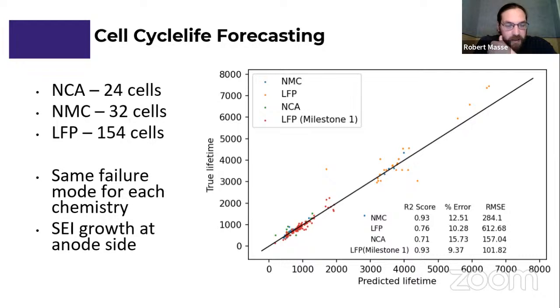chemistries. NCA, that's nickel, cobalt, aluminum. NMC, nickel, manganese, cobalt. LFP is lithium iron phosphate. These are 3 of the most common cathodes for batteries today. What we were able to find is that since the anode side is where the main failure mode is, that being SEI growth on the anode side, on the graphite anode, the features that have been engineered for this particular application are indicative of and correlate with SEI growth on the anode side.